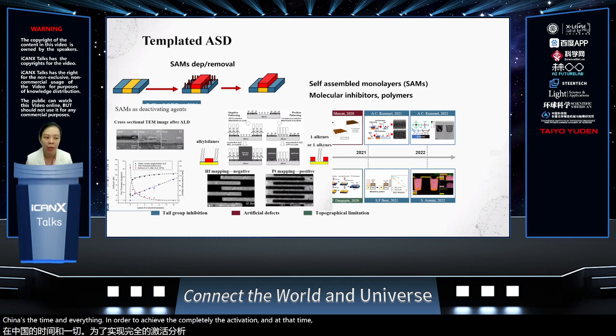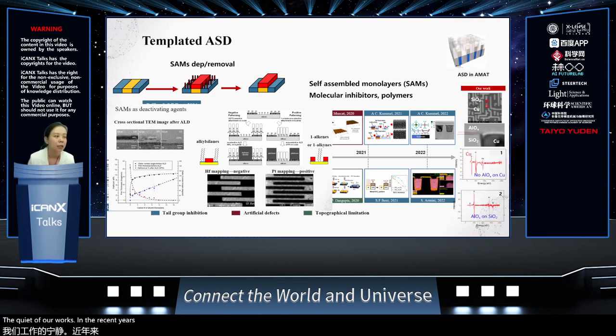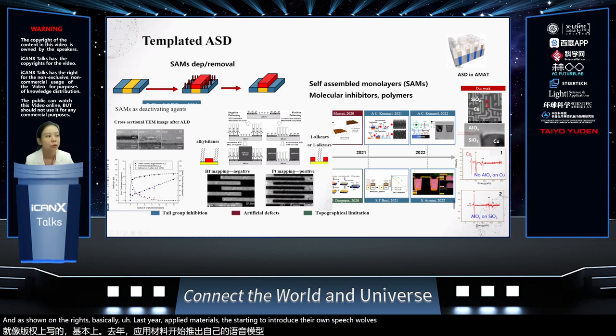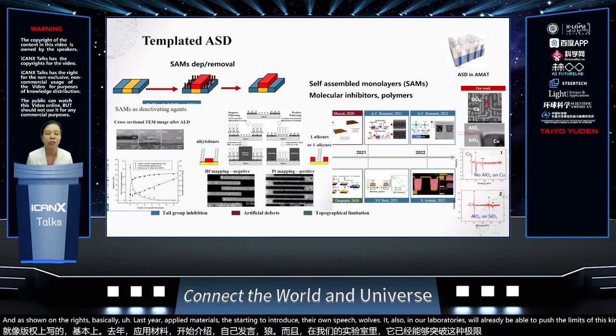And at that time, we'll be able to apply this technology to obtain this kind of self-aligned growth of either metals or oxide. And this actually aroused a great interest from both academia and industry. And afterwards, there have been quite a lot of works in recent years, and as shown on the right, last year Applied Materials started to introduce their ASD tools, and also in our laboratories we're already able to push the limit of this kind of self-assembled monolayers down to a few nanometer scales.